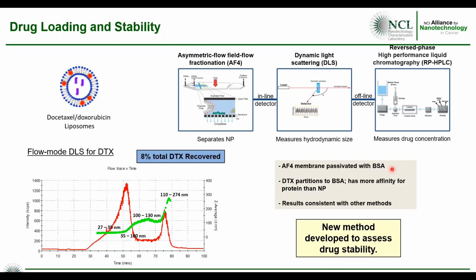If we look at the other drug, docetaxel, in this case, we're only seeing 8% total recovered across all these peaks. And the reason being is that if you're familiar with AF4, you typically passivate the membrane with bovine serum albumin, a protein, before you start running your actual sample. In this case, the docetaxel partitions to the BSA, so it has more of an affinity for the protein rather than the nanoparticle. And this can be used to basically assess drug stability. So if you think about it, if you inject this into your body, most likely the drug will be released to the plasma proteins. And this method kind of gives you an idea of how much it releases to the proteins. And we published this in this paper shown here. So it's a method to assess drug stability.